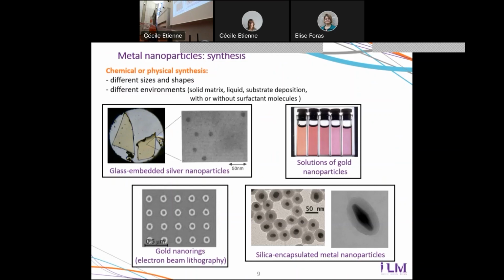So for instance, here is an example of a glass doped with silver nanoparticles. Here, these are solutions, so water plus nanoparticles in it, which give a color very different from that of water to the solution. Here, you have nanoparticles which have been produced by electron beam lithography on the surface. These particles are gold nanorings, and they are regularly spaced after the fabrication process.